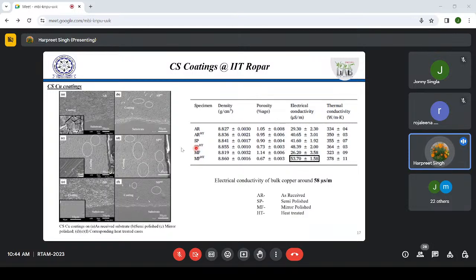So we are showing the effect of heat treatment, as I was showing you, that these deposits can be heat treated and you can get better adherence and better electrical conductivity. As I told you, this is the same study where we made copper coatings on stainless steel, and our objective was to achieve electrical conductivity of this level, and we could achieve it after heat treatment. This is quite understandable, that both will improve. Thermal conductivity as well as electrical conductivity can be improved after heat treatment, because that will merge some of the boundaries and you can get better conduction and so on.